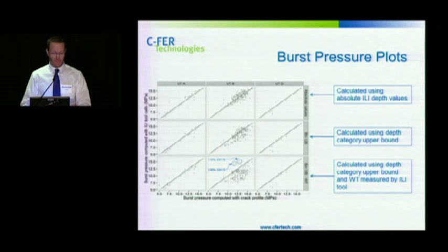The next slide is going to show a couple details of data points and how they work out like this. But as you go from the bottom to the middle to the top, what we've done is we've calculated the burst pressure in different methodologies using different assumptions. And so the top one is not conservative at all. It's pretty much right in the middle. And in that case, we use the absolute depth values that were called by the ILI tool. There often isn't a spec around these numbers, but we wanted to see how they compared with the excavation results. And you can see that in this case, there's very little bias and there's fairly good correlation with the numbers.